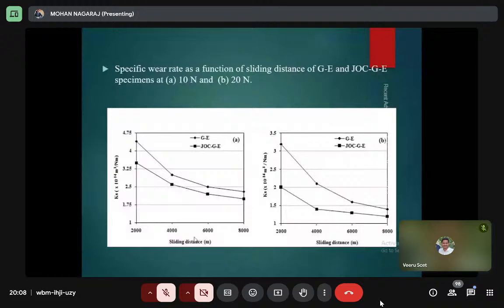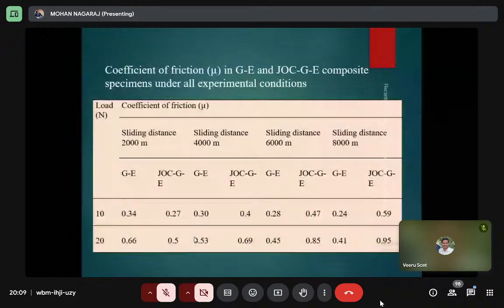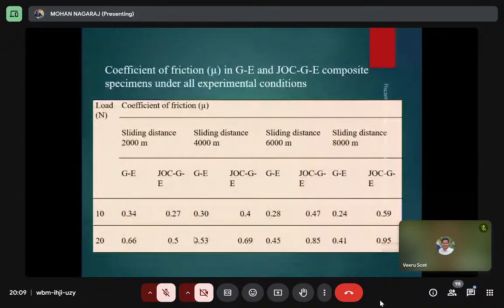Here you are observing the glass epoxy composite and the JOC filled composite. It gives more wear resistance in the specific wear rate you observed. Say A and B. A is the lower Newton load, and B is the higher Newton load. So this is the coefficient of friction, which shows mixed fractions we observed, but as compared to glass epoxy composite, the oily nature of the Jatropha oil cake gives a very good coefficient of friction as compared to the general composite.